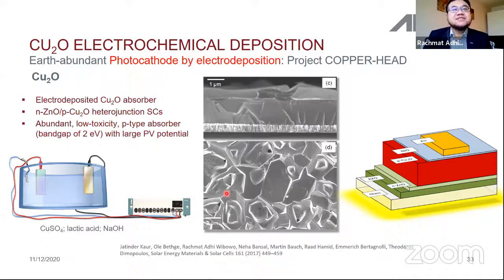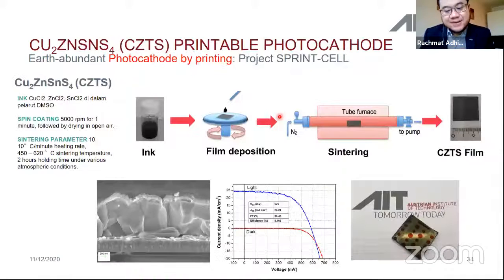And then what we see after deposition is this layer, which is really compact. I think the deposition time is about 30 minutes. It depends on the voltage, so I can reach about 2 micron thick of cuprous oxide. This is really interesting because it works as a photocathode, because this is a P-type material.